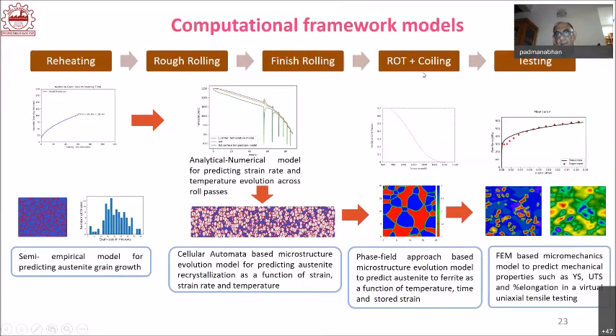And then, when it comes to runout table and cooling, in the runout table, only the temperature is brought down. And then it is coiled at a temperature which is convenient. And therefore, you can use the phase field model in order to get the microstructure evolutions and predict the austenite to ferrite transformation, again, as a function of temperature, time, and stored energy. And then you go into virtual tensile tests, predict yield stress, ultimate tensile strength, percentage elongation, and so on. This can be done. I will explain it a bit more in the next slide.